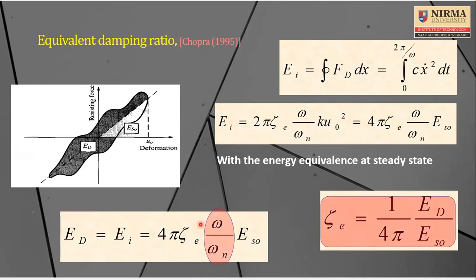And the most important parameter here is omega by omega n. There is always some forcing frequency, and the system has its own natural frequency. So in order to establish this energy, we always treat this ratio omega by omega n as equal to 1. It means you are always considering the frequency as a resonating frequency, and that is a very, very important assumption as far as establishing the equivalent damping ratio.